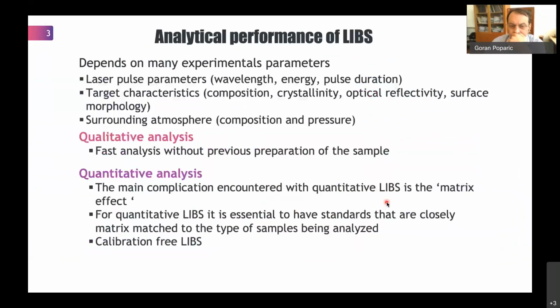The analytical performance of LIBS depends on many parameters, such as laser pulse parameters, sample characteristics, especially surface morphology and optical reflectivity, as well as the surrounding atmosphere. Qualitative analysis can be pretty much straightforward without previous preparation of the sample.